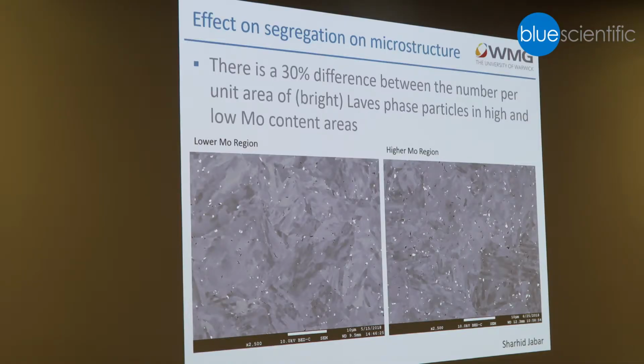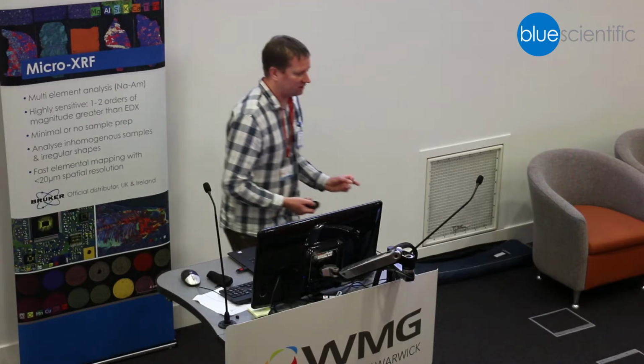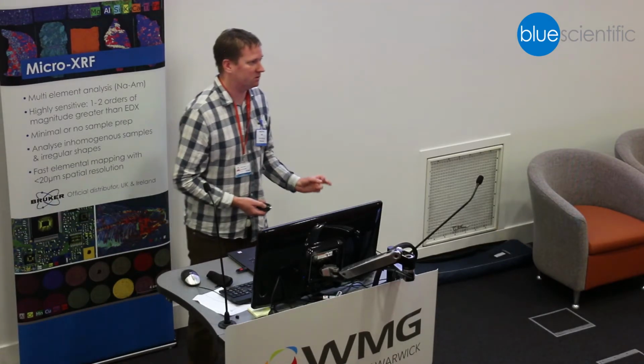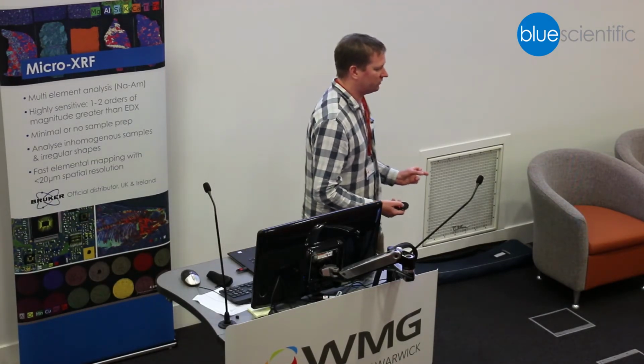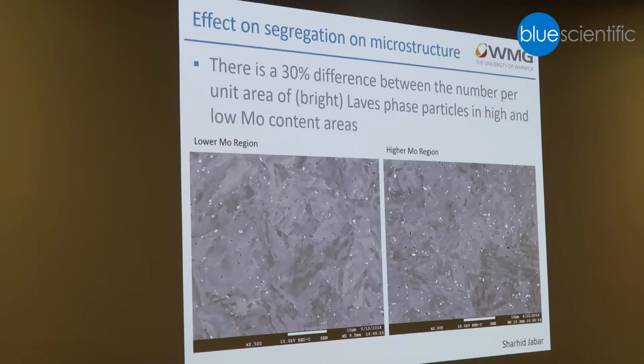And why is that important? One of the things we're trying to do on this project is we're trying to quantify microstructural features. For example, here we're trying to quantify second phase particles. And if we compare an area where we've got a lower molybdenum content with an area with a higher molybdenum content, there's a 30% difference. Also, the segregation characteristics of elements like molybdenum will also follow with segregation of more tramp elements as well. So it helps us know where to look for certain types of features.